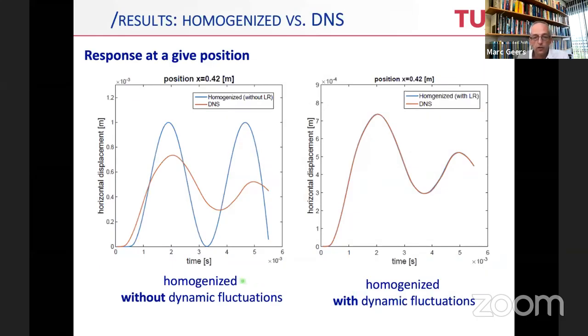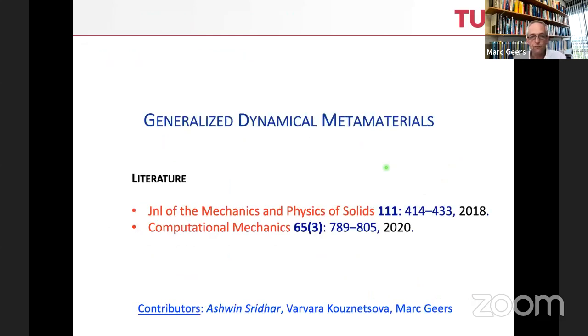Here again, a static picture at a particular fixed position where we actually see the time evolution. So we're at position 0.42 meters and we see how the wave evolves in time. Again, in blue, that's the standard homogenization without resonance. In red, the DNS solution. And on the right, the comparison between DNS and the enriched continuum in which the eta fields play a role. So what it all shows is that this seems to work fairly well.